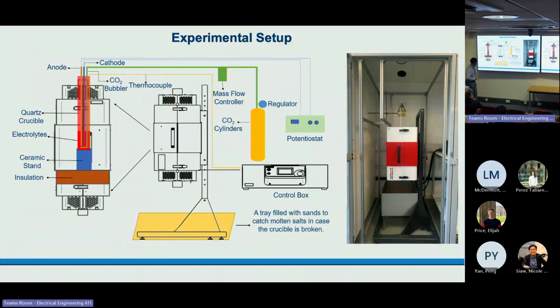So this is the experimental setup we used to investigate carbon nanotube production from CO2 using high temperature electrolysis. The main component of our experimental setup is the furnace, as we can see from this picture. It's a vertical tube furnace. We put an alumina crucible inside of the furnace, and we use thin alumina tubes to wrap the silver wire to connect the two electrodes inside the alumina crucible. We put carbonate salt inside the crucible and use the tube furnace to heat it up to 800 degrees to make the carbonate salt melt.